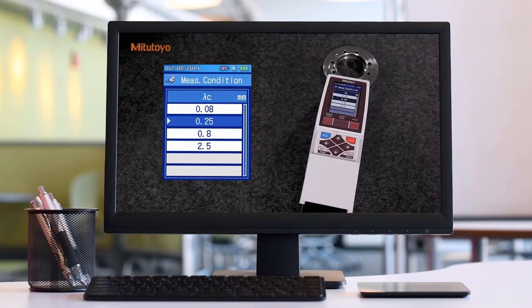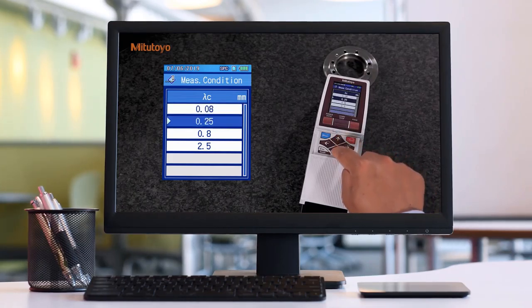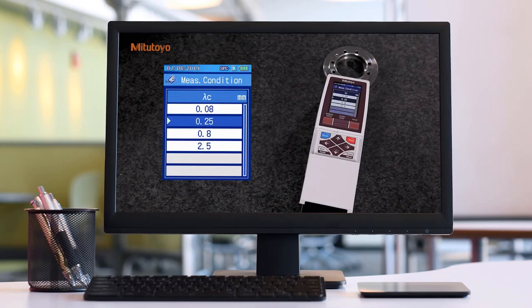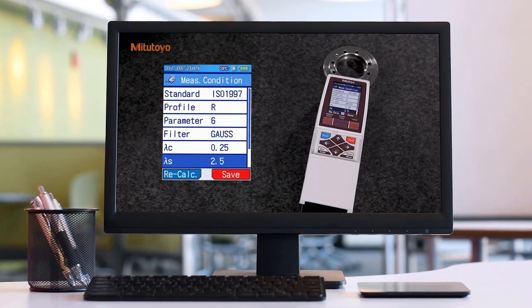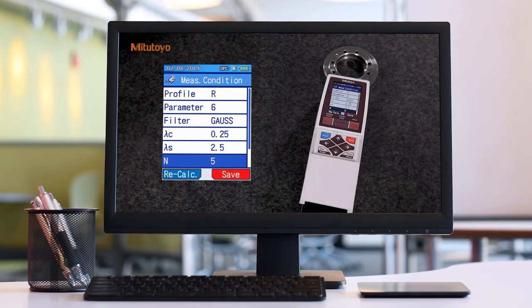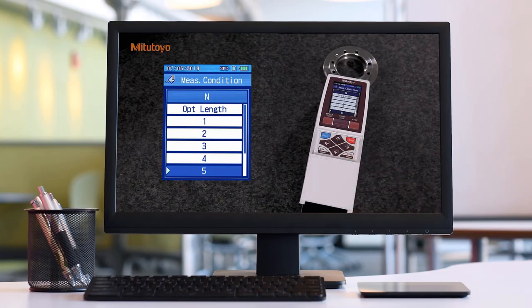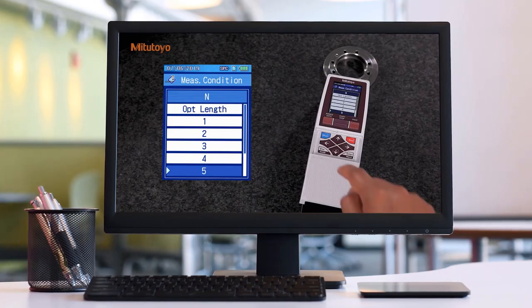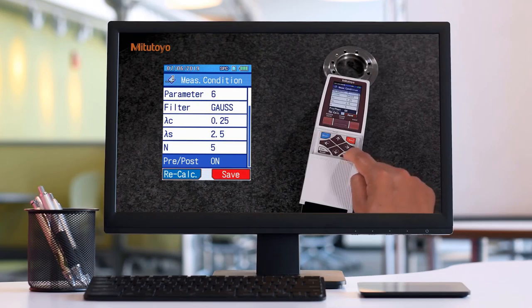The selection of filter depends upon the tolerance mentioned in the technical drawing. ISO 4288 provides guidelines for selecting the required filter. In this case we use 0.25. The SJ-210 automatically chooses Lambda S according to the selected Lambda C. N is the number of sampling lengths; according to ISO standard, 5 is the default, but it can be changed in the SJ-210. Pre-post travel of the detector during measurement can also be switched on or off.